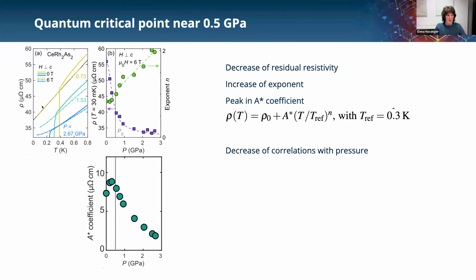At the same time, the residual resistivity decreases. This is shown here in violet. And the A coefficient, which we analyzed in this way because we have this open exponent, shows a peak as it should when we reach a quantum critical point, and then decreases, and this indicates a decrease of correlations with pressure.